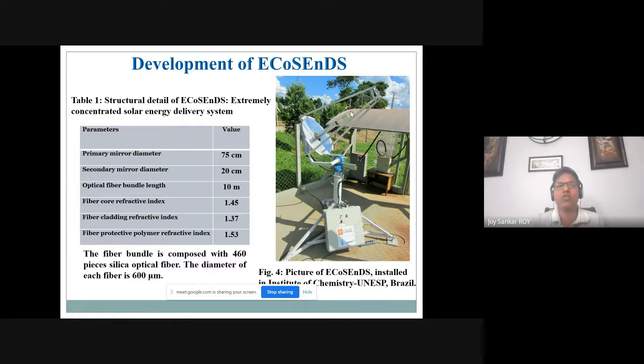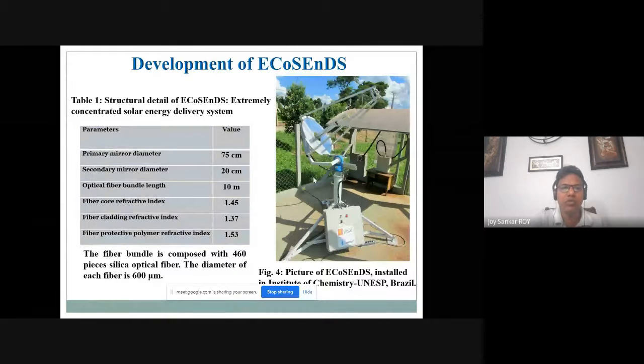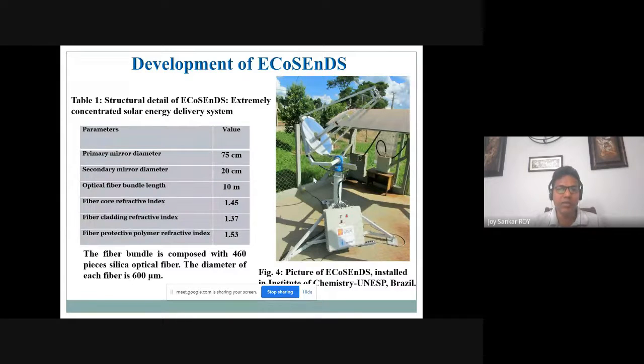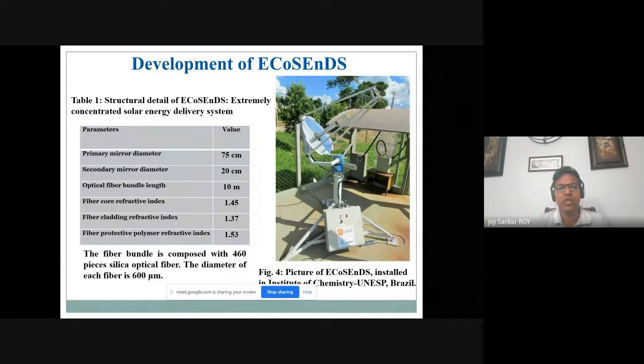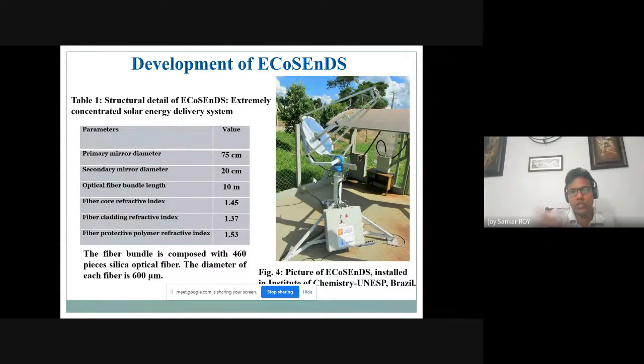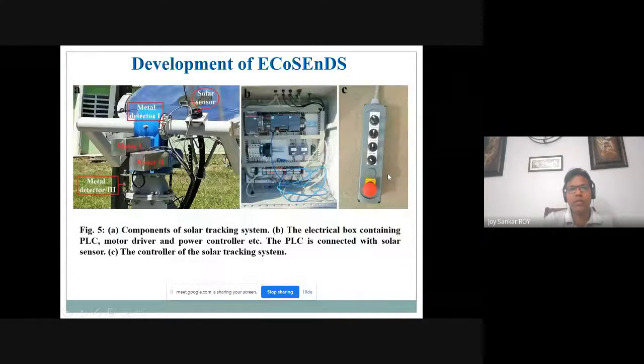So it is very highly concentrated sunlight. In this case, the core of the optical fiber is glass with a refractive index of 1.45, and we use a low-index cladding of 1.37. So the cladding's refractive index is lower, which lets us guide the light in the fiber. We put another protective polymer, with refractive index 1.53, to protect the whole fiber and maintain good flexibility. For this system, we made the fiber bundle with 460 silica fibers, each 600 micron in diameter. This is the highlight of what we have developed.